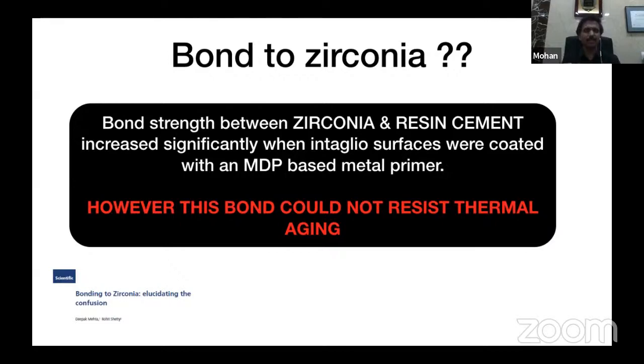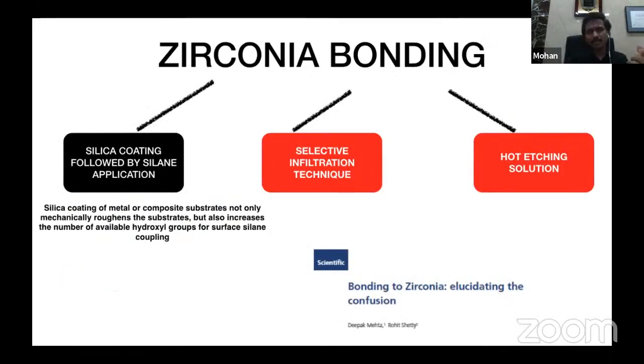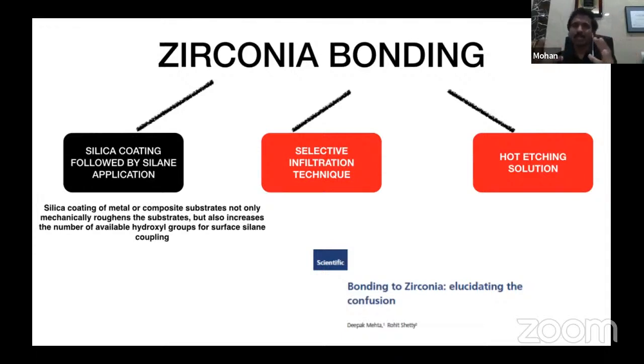So if I've seen a restoration, what I've done or what somebody else has done, I would strongly suggest they replace the restoration rather than playing around with the zirconia restoration. Anything else I would love to repair, but not zirconia, because the bonding is always a big failure. There were a lot of studies done on zirconia bonding, and they found that these are quite impractical or literature based. Silica coating can be slightly practical, but the selective infiltration technique and hot etch solution, with a special solution which in the study they have designed, is more of a theoretical point of view, that's why I put that in red.